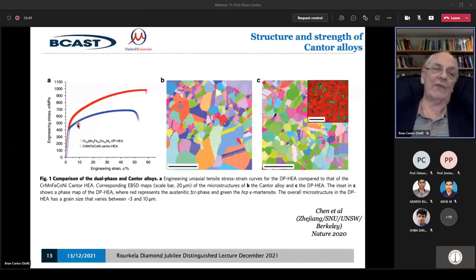Now, if you have a ceramic or a polymer or a metal which has got too much alloying in it, they become very brittle. In other words, what happens is they move up elastically and then they fracture. So you get a high strength, you go up to high levels of stress, but they don't have any formability because they just fracture the minute you try and change the shape. If you have an ordinary metal like pure gold or copper, you don't have to go very, very high up here before they start to deform plastically. The atoms roll over each other, as I said, if they're face-centered cubic, or even body-centered cubic, but mainly face-centered cubic. Gold, lead, you can deform them a long way. You can get a lot of strain. You can change their shape a lot.